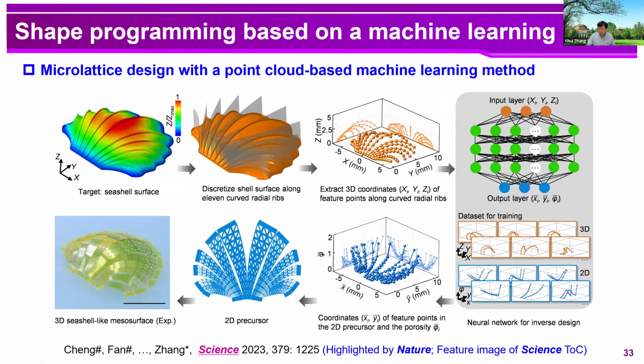So if the target surface cannot be discretized into a group of developable ribbons, the beam theory I just showed will not work. And in this context, introducing a machine learning algorithm allows us to develop a more general inverse design method for 3D surfaces with general symmetries or without any symmetries. And in particular, we exploited a point cloud-based neural network to predict the 2D point coordinates and the porosity distribution for a prescribed set of 3D coordinates. So in this example, you can see that this method works very well for seashell surface. And in this example, we divide the entire surface into 11 undevelopable ribbon components.